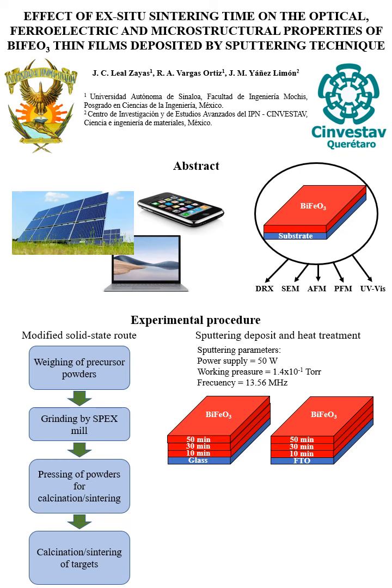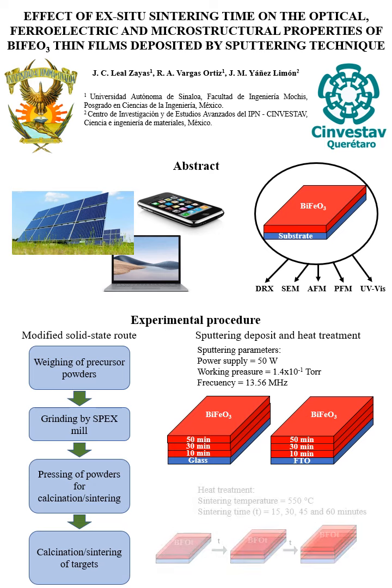These deposits were carried out onto two different substrates, which were glass and FTO, and the deposit process consisted of three stages with different times, which were 10, 30, and 50 minutes. And a heat treatment was carried out between each layer of deposit at 550 degrees Celsius with different sintering times, which were 15, 30, 45, and 60 minutes.